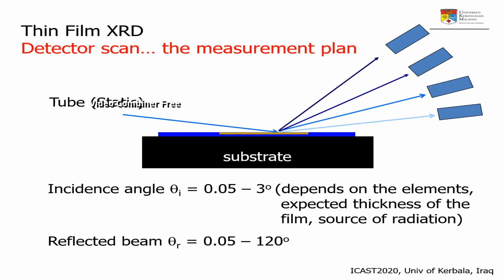In detector scan, the X-ray tube's position is fixed at low angle, usually between 0.05 and 3 degrees, depending on the film. On the opposite end, the detector moves from 0.05 degree up to 120 degrees. The red colored knife edge at the center is used to block some of the X-ray beam and thus shorten the X-ray footprint.